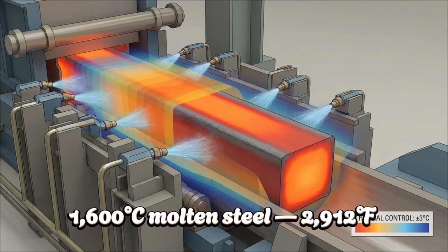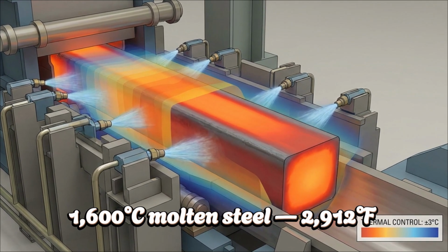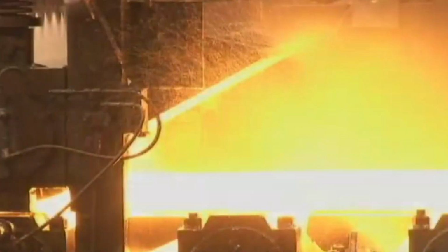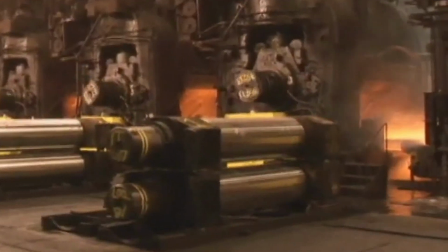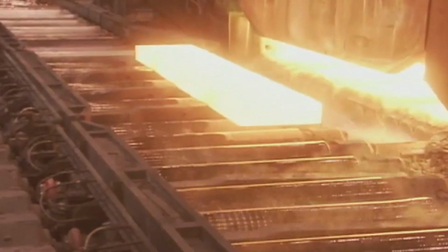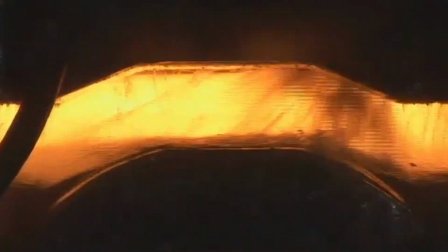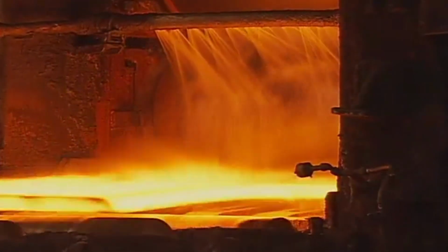From 1,600 degrees Celsius molten steel, 2,912 degrees Fahrenheit, to a precisely cooled beam, every meter of structure depends on thermal symmetry, controlled cooling, and a shell just millimeters thick. That's how continuous casting and rolling turn liquid metal into the beams holding the modern world.